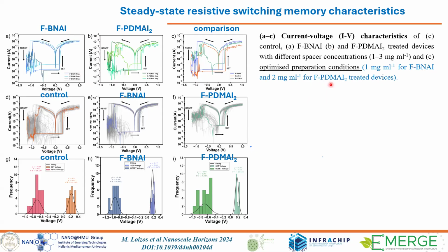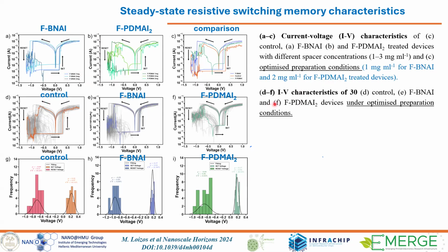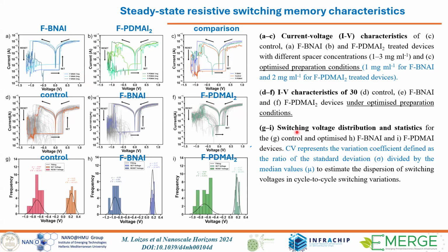And for the best thickness, we fabricated many devices, at least 30. This is the reference devices. This is 30 devices with BNA, and then at least 30 with PDMA. And we extract all the statistics of the devices, and we monitor the set voltage, for example, compared to the reference device, and also the variability through this CV parameter. What we call variation coefficient, CV parameter, is actually the ratio between the standard deviation and the median values for each data set.